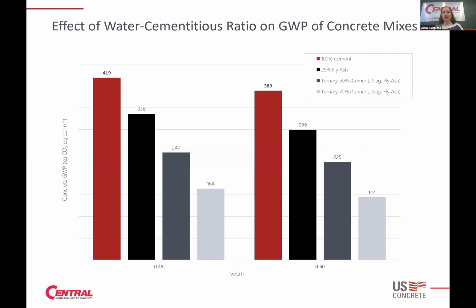And this just shows an example of water cement ratio. If that is limited at a pretty low number, lower than what's needed for the strength that's needed, you're actually pushing up the embodied carbon of the mix, and unnecessarily in a lot of cases. So what this shows is 4 mix examples at a 0.45 water cement ratio. And when you look at those 4 mix examples at a 0.50 water cement ratio, you can see that there's about a 7 to 12% reduction in the embodied carbon of those mixes.